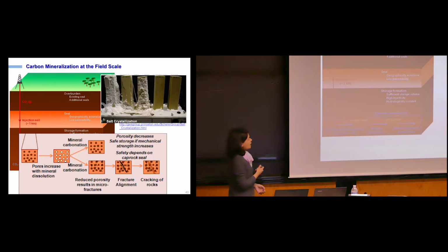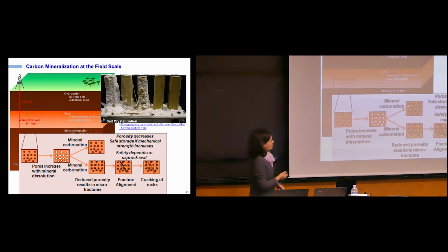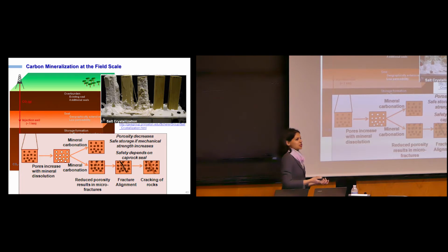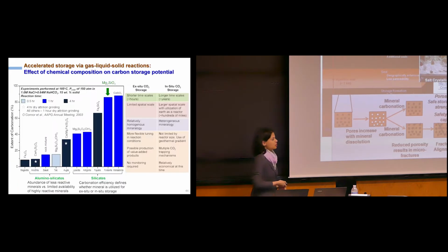Turns out that if we actually inject CO2 into some of these reservoirs, we could completely carbonate some of these reservoirs over a timescale of about 1 to 2 years. This is something that folks have actually observed in places like Iceland, where they're doing CO2 injection projects. Chances are that it's great for storing CO2, but we still don't know what that's going to do in terms of fracture propagation in these materials. And what you don't want is to have fluids bearing salt getting trapped in some of these pore spaces, the water being evaporated, salt crystallization occurring and these materials disintegrating and falling apart.